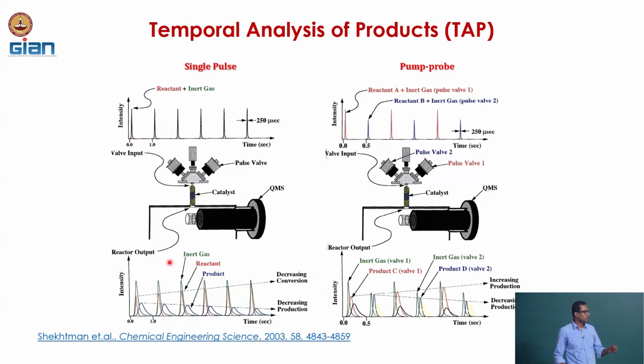the product evolution. So, from pulse 1 to pulse 2, just because we are addressing a very small fraction of the total number of sites, there is not going to be a significant difference, because it is a very small fraction. But pulse 1 versus pulse 10,000, there is going to be a significant change, correct. And then with a series of pulses, we can actually look at how the catalyst structure is evolving, and based on that, how my product distribution is changing. That is what is roughly shown as an example here.